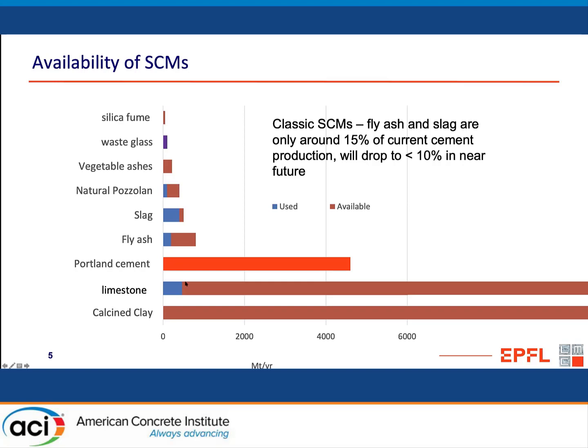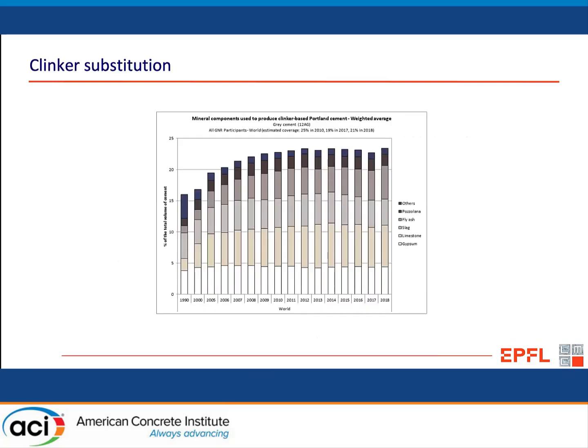Now I'm going to come back a little bit to limestone and calcined clay because these are the things that can really unlock this. So if we look at this graph here, this shows you that in the past few decades, particularly since the 1990s, we have been using increasing amounts of substitution in cement. And this is by far and away the most practical and fastest way to reduce CO2.